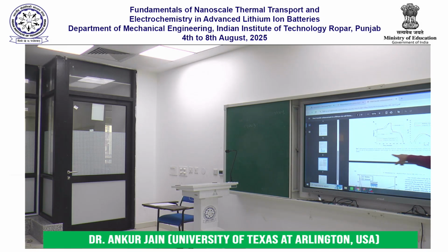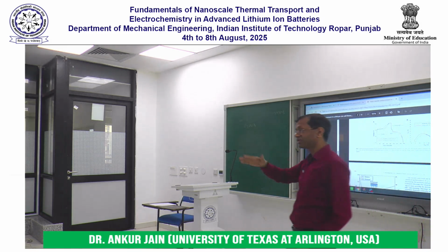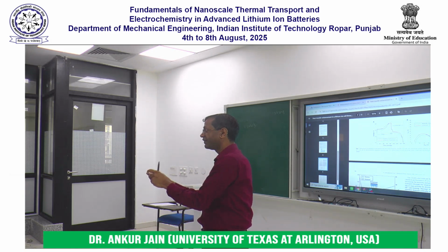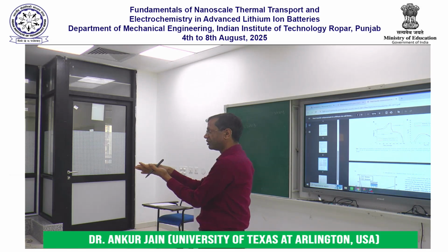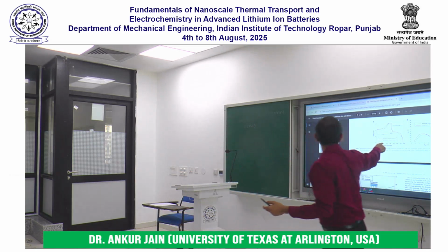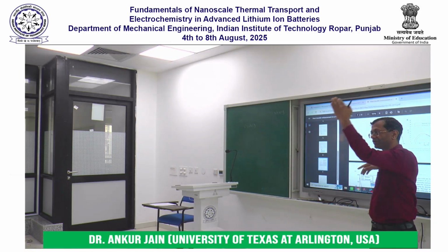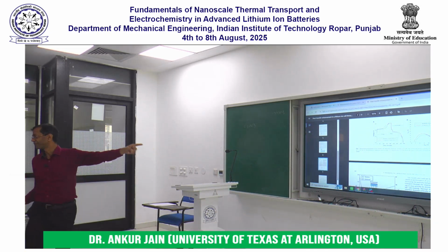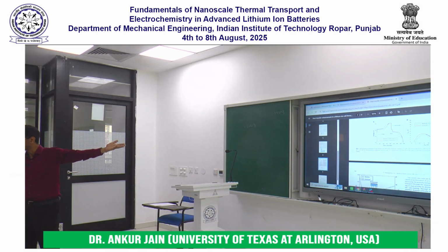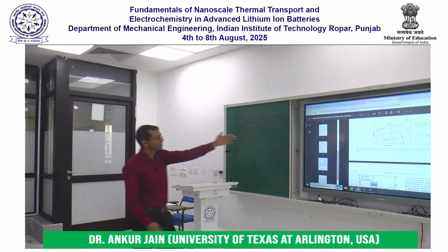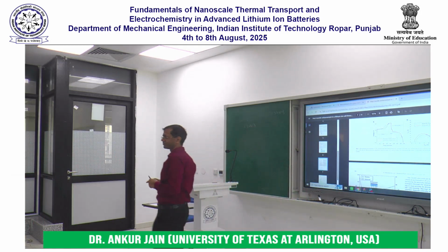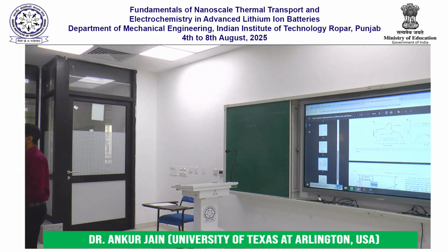So we used lithium anodes. We purchased lithium anodes because this was all being done on the cathode side, so the lithium anodes were the same. On the cathode side, we used a baseline cathode separator, and we used one including the aminosilane molecule. This experiment was done with electrolyte. Of course, we need electrolyte in order to charge and discharge the cell. So this experiment was done in the electrolyte, and we found that the two were nearly the same. Everything was identical, and it was done using a standard process.